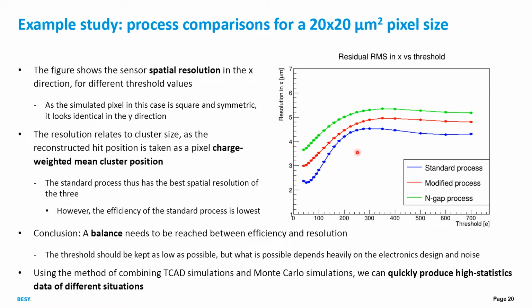However, it's important to remember that the efficiency of the standard process is the lowest. So in conclusion, basically, we need to reach a balance between efficiency and resolution. We want high efficiency more than we want high resolution, really, but we really want both. So it's important to keep the threshold as low as possible, but what is possible depends heavily on electronics design and noise. Our current baseline is around 200 electrons. But the point is that if we use the method of combining TCAD simulations and Monte Carlo simulations, we can quickly produce high statistics data of different situations, which is nice.